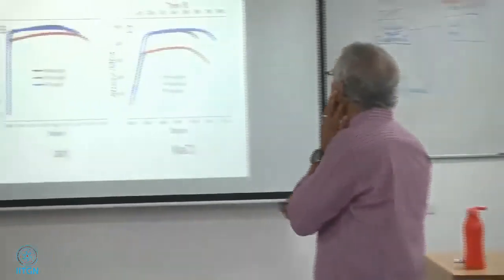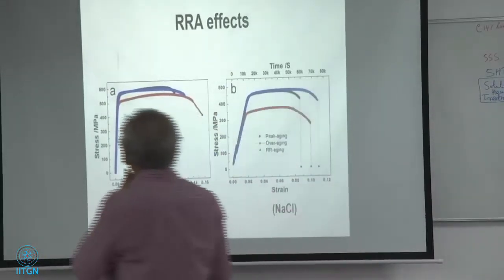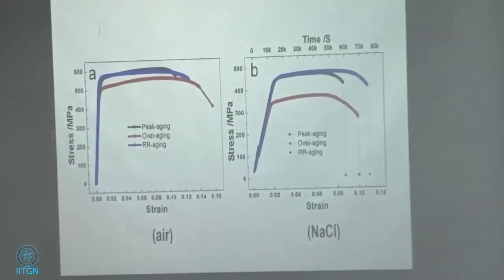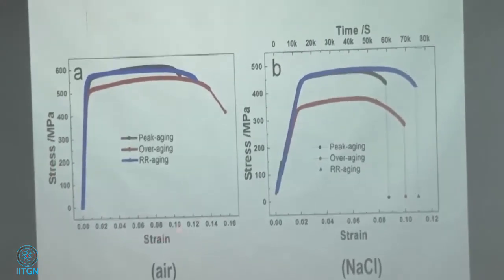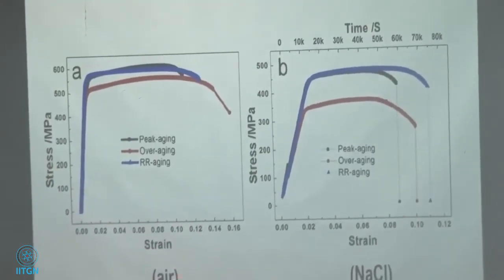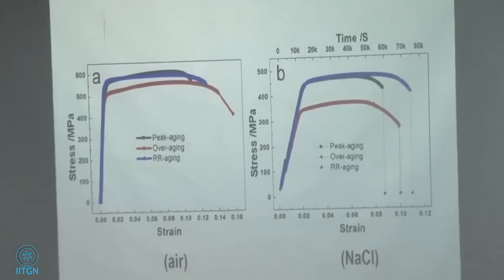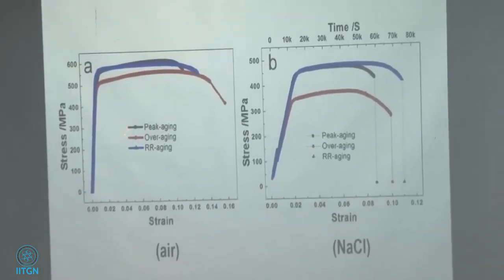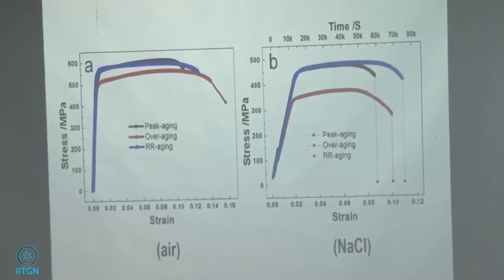So here is the work done by somebody. Usually I'll put a reference here, but I can tell you what it is. So here, look at it. This is the peak aged in black. So this is the strength versus strain. Stress strain curves in air and in sodium chloride solution. Let's look at air. This is after you do the retrogression reaging, okay? There is your peak aged. There is your retrogression reaging. There is your overaged. Right in between, just about, and you got the same strength as T6. Okay? You got the same strength, right?